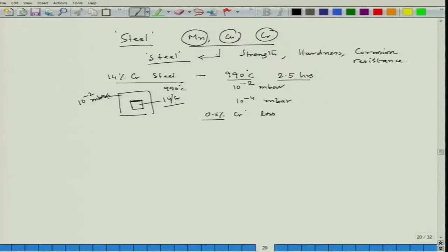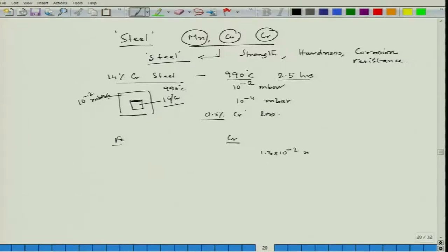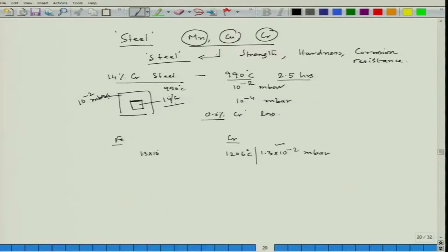The reason for this chromium loss is that chromium has a higher saturation vapor pressure than iron. For example, chromium achieves a saturation vapor pressure of 1.3×10⁻² millibar at 1206°C, while iron requires 1448°C to reach that same saturation vapor pressure. This means chromium vaporizes more readily than iron at the same temperature.